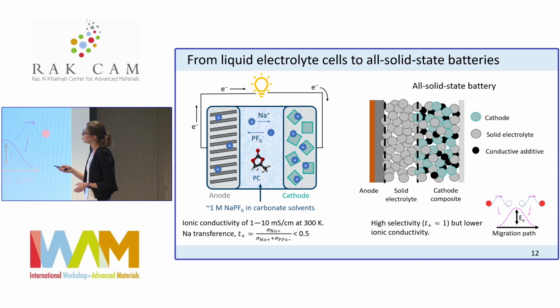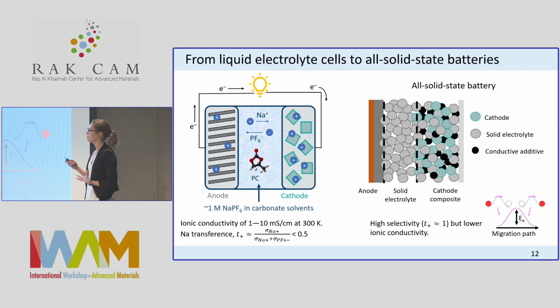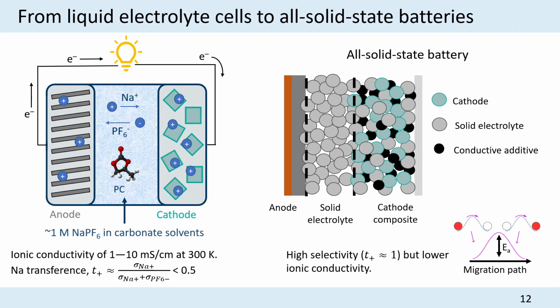So there are ways we can solve some of these issues of liquid electrolytes by moving to an all-solid-state battery that has a solid electrolyte instead. One of the things that will be improved is the flammability. These solid electrolytes are not flammable. Some of them have a better electrochemical stability window than liquid electrolytes, especially at high voltage. And they can be very selective to sodium transport. So now you're getting to a transference number much closer to 1.